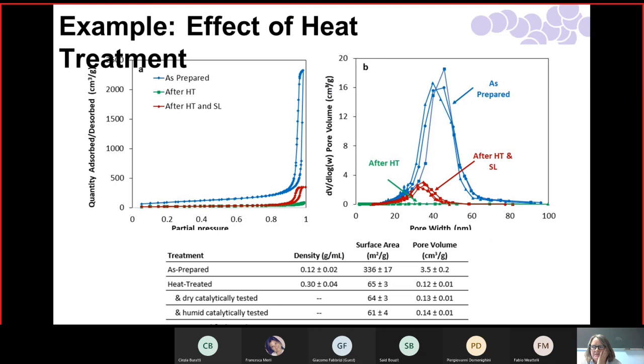How do I go back? I will, I think, finish with just some examples. So we make aerogels. These are catalytic aerogels. These ones are copper and alumina. So instead of silica, we make an alumina backbone, and we soak the alumina wet gel in a copper salt solution. And Mary Carroll talked a little bit about this. And that creates some copper nanoparticles in the material. And these are useful in catalytic applications.